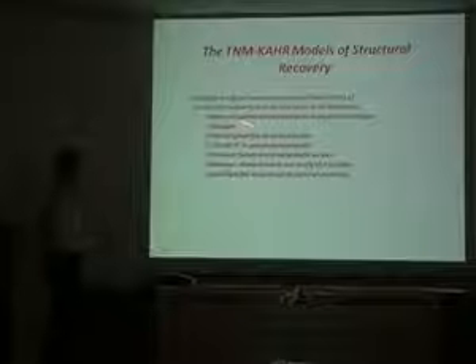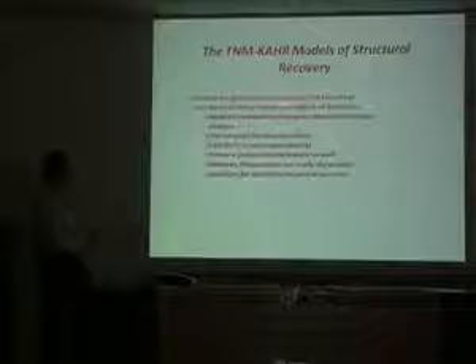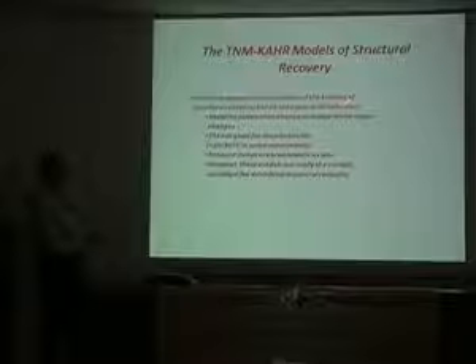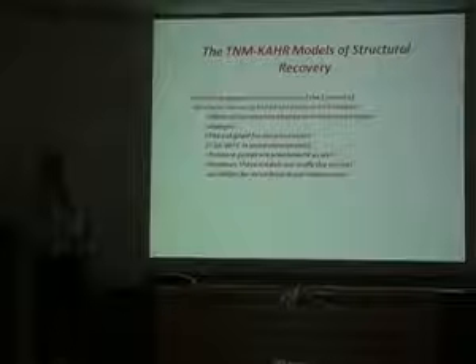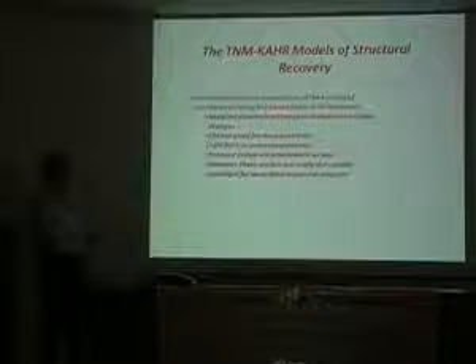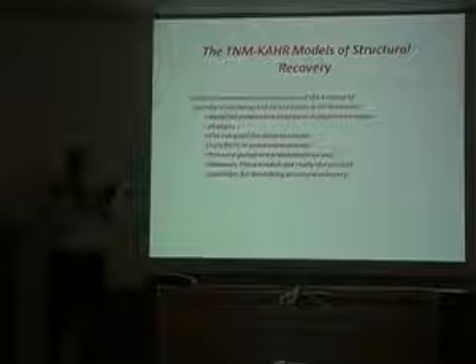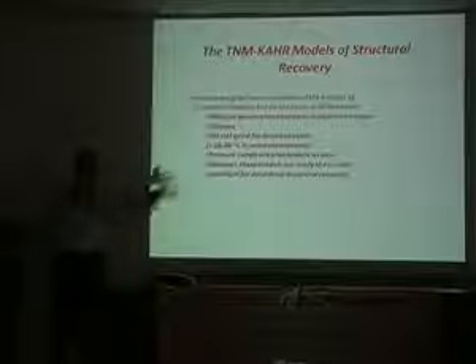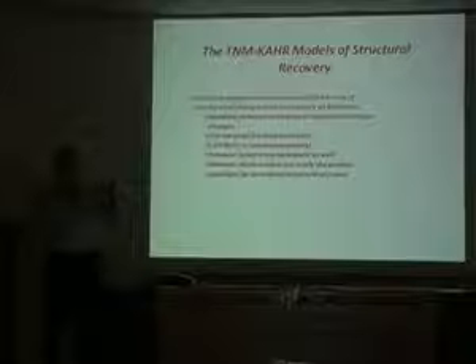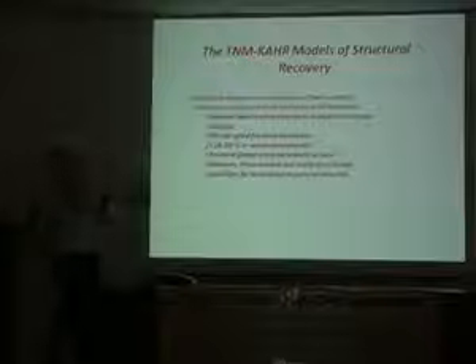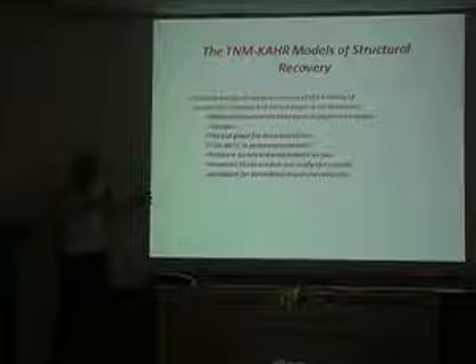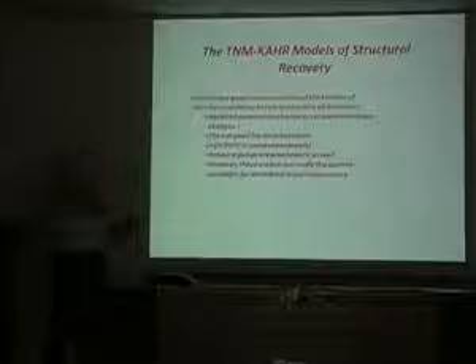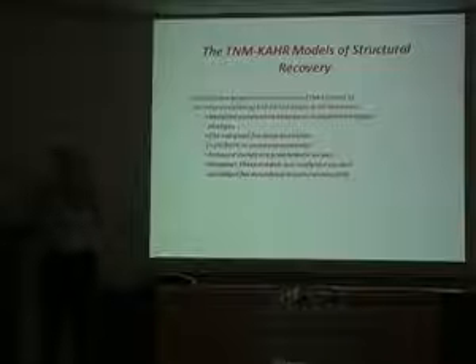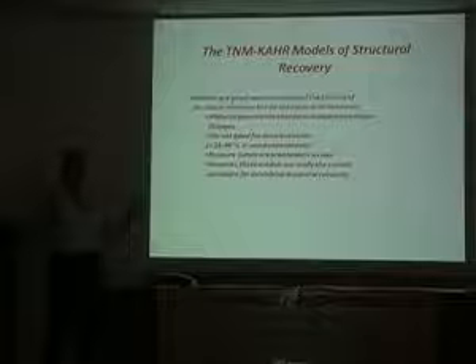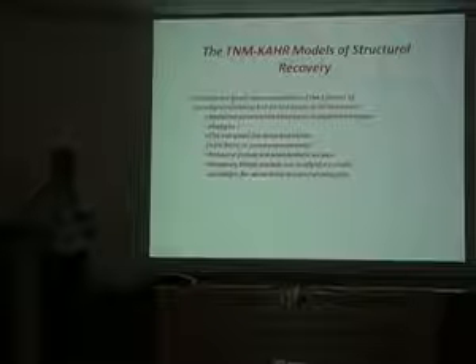So the models are good representations of the kinetics of structural recovery, but they don't capture all behaviors. Material parameters can change as the temperature range changes. If I fit data in about a 15-degree temperature range, and then go to a 20 or 30-degree range, what I find is the parameters change. The parameters are not constant. So that's actually an important thing.